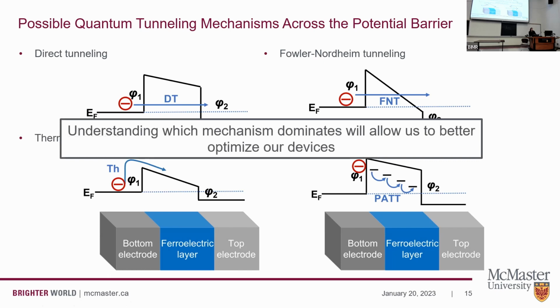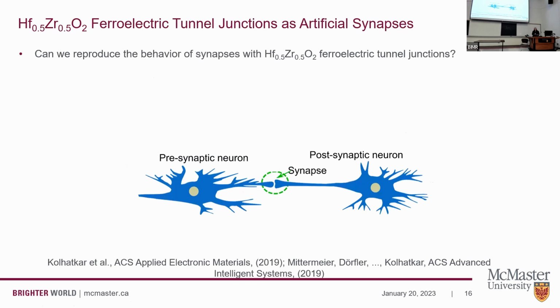So all four mechanisms can be at play, and we want to understand which one dominates, because understanding which mechanism dominates will allow us to better optimize our devices. So the 0 and 1 resistance states, the high and the low resistance state, confirm that the devices were suitable for non-volatile memories. However, as you probably know, our brains are not restricted to 0 and 1. We don't think in 0 and 1s. We don't have only two resistance states, but actually many different states in between.